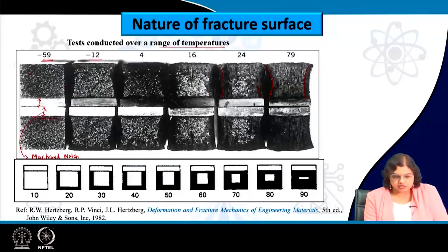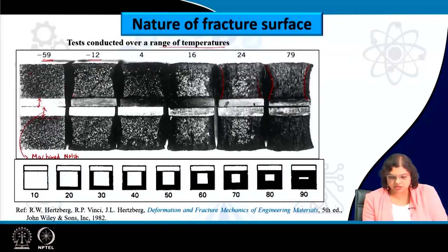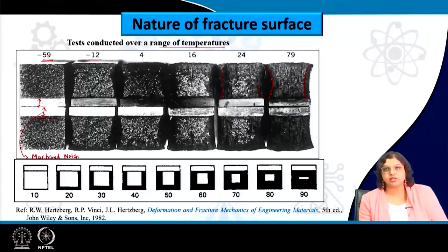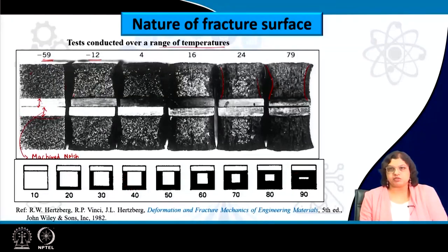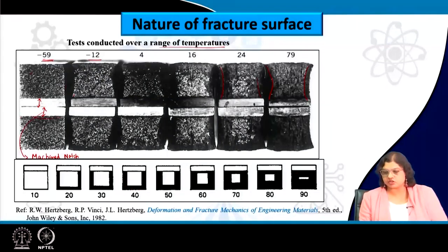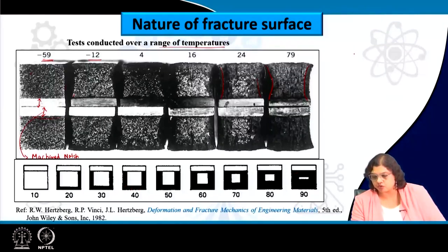For quantification, this is the schematic representation: for some cases we see a flat fracture with no signature of shear lip, while repeating the test at higher and higher temperatures shows increasing shear lip formation, until most of the fracture surface is completely covered with shear lip — which can happen for very ductile materials. To find the percentage of shear lip we need to measure and quantify it.